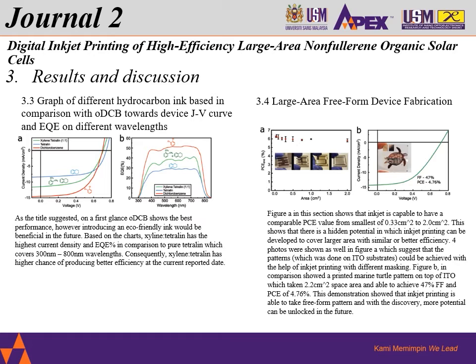And then lastly, from the results and discussion, this figure shows the PCE chart across different areas. Multiple devices were printed with different areas, and the biggest area that was achieved during this inkjet printing was 2.0 centimeters squared. From this chart, you can see that with the smallest, which is 0.33 centimeters squared, we are achieving around 6% PCE. But when we increase the area size itself, the PCE is actually comparable.